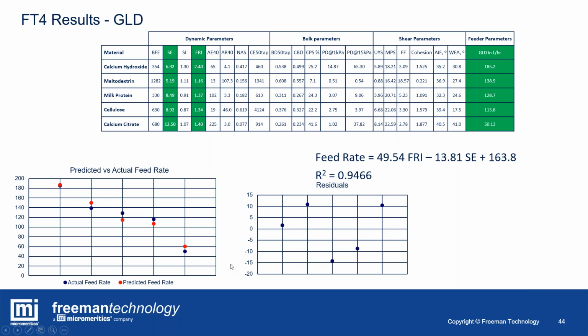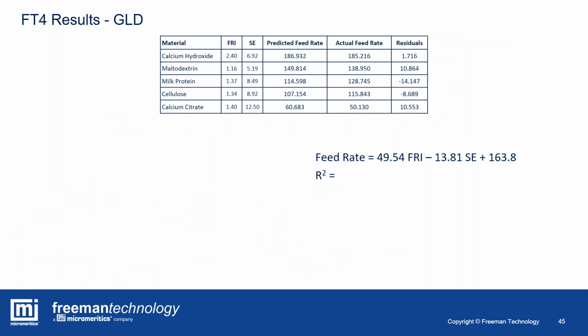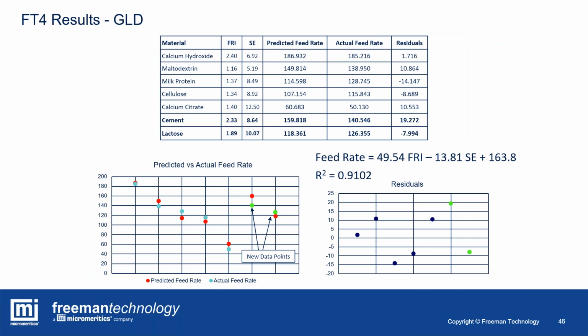But of course, we built that based on the parameters we've characterized here. So what we wanted to do was take 2 new materials that weren't part of that model, put them into the equation, and you can see our R squared is still 0.91, so 91%. Cement and lactose, very different materials to each other and to the rest of the set from which the model was built, and you can see a reasonably decent correlation between the predicted and the actual observed feed rates.